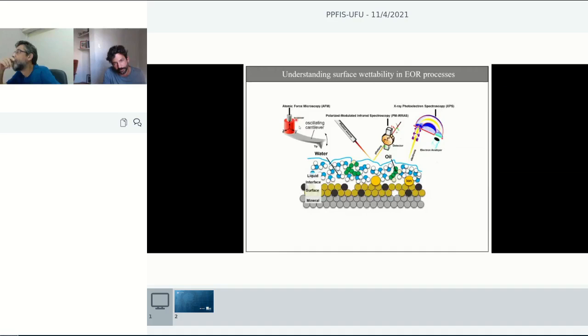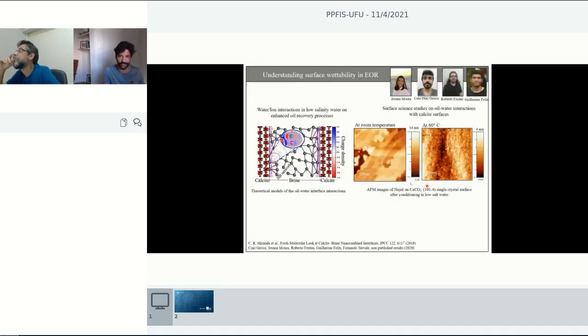So, and then for that we apply a lot of different techniques. Again, we use this methodology with AFM, FTIR, and XPS. And in this case, what is interesting here is to look at how the molecules absorb on the surface. This is a theoretical work, very interesting, from Caetano Miranda from USP that supports a bit of our work. And then here is some experimental data that you see at room temperature and then 60 degrees, how this relatively simple oil interacts with the calcite surface.